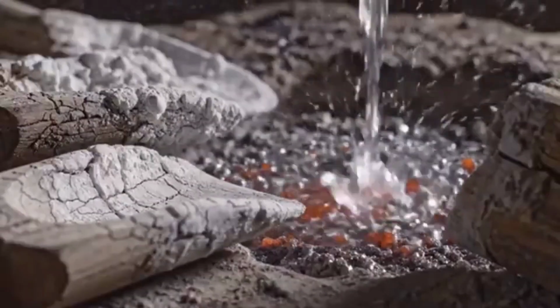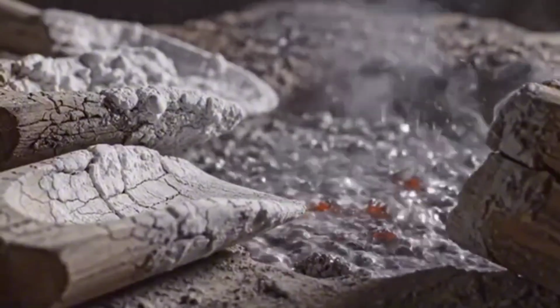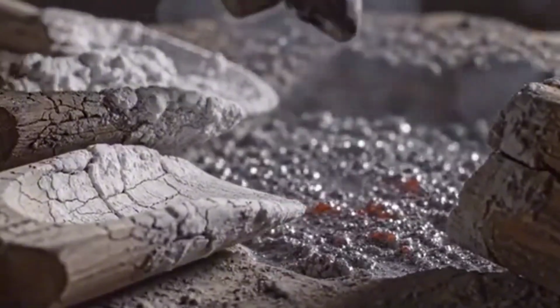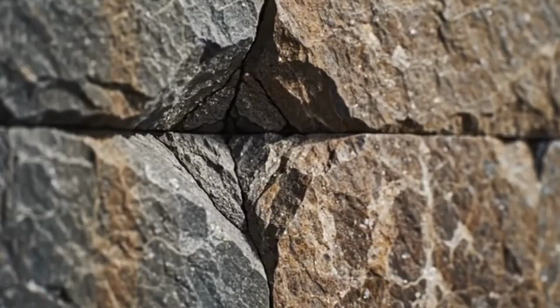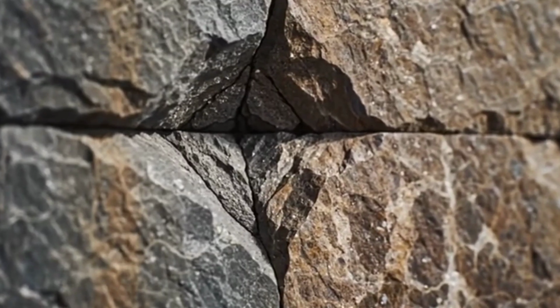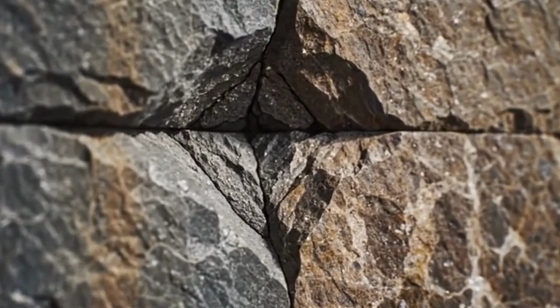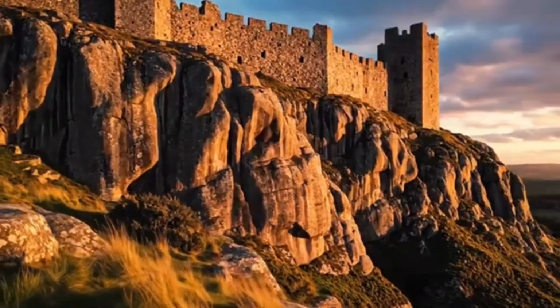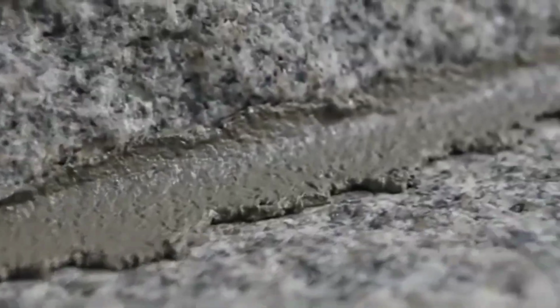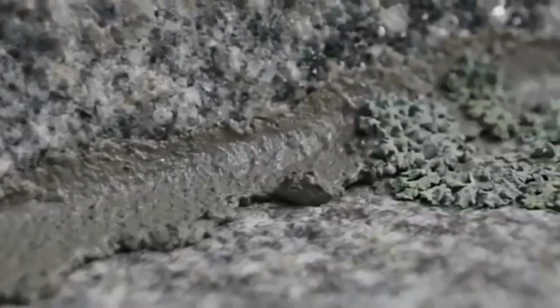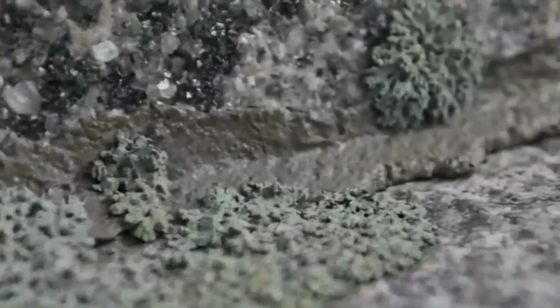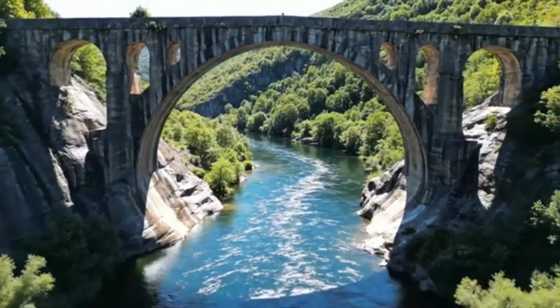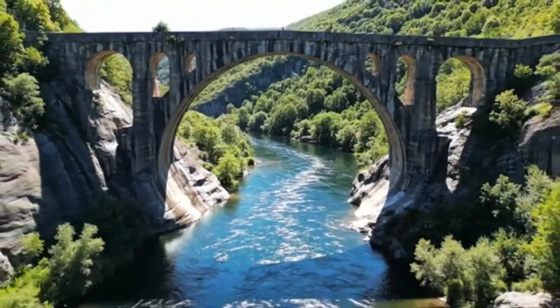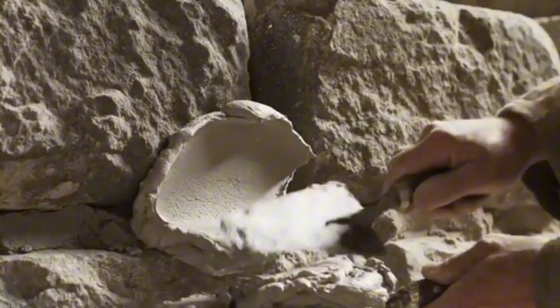Here is what happens when Roman concrete cracks. A fracture forms, rainwater enters, it reaches a lime clast. The water dissolves the reactive calcium inside the clast, creating a calcium-rich solution that flows along the crack path, filling the gap from the inside. Then it recrystallizes as calcium carbonate, a strong mineral that bonds to both sides of the fracture. The crack seals shut, but it doesn't stop there.